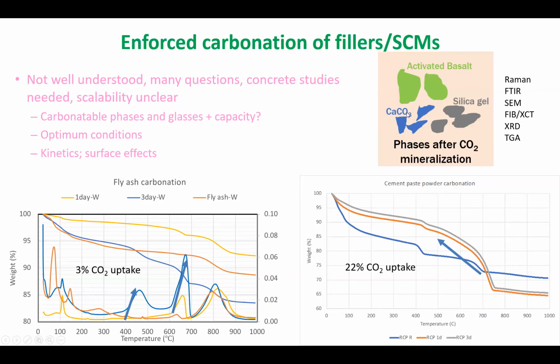Again, bulk techniques like XRD, TGA, FTIR will only get you so far. So you kind of need to use XPS, XCT may or may not be good enough, not sure about the resolution, but FIB, XCT, Raman, etc. The technology is needed, maybe even TEM, to really understand this depth of carbonation kind of phenomenon and how that varies, and what implications that has to the CO2 uptake.